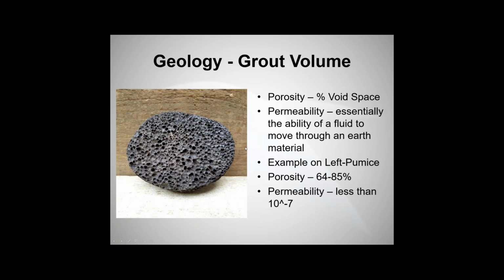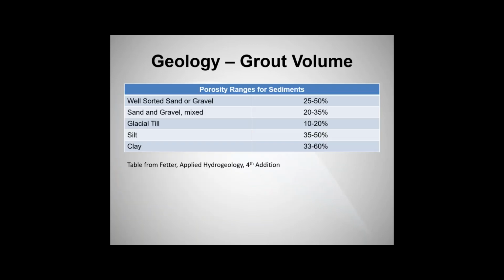Permeability is essentially how well connected that void space is, and how easy it is to push a fluid through it. When you look at this pumice, the porosity, the void space, is typically 64 to 85% for a specimen of pumice. However, the permeability is very low, less than 10 to the -7, which essentially means you can't push much through that. So even though you have a very high porosity, the amount of material that you could push in that space would be very low. Britt had a better chart than I did on this, but again, I wanted to make this example. You can see on the top here, you've got sands and gravels, where typical porosity ranges from 25 to 50%.